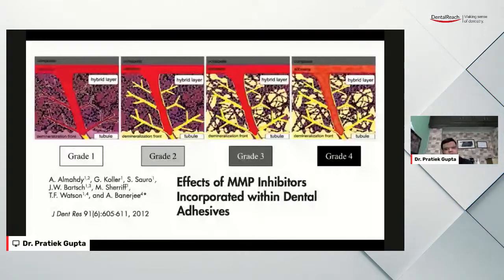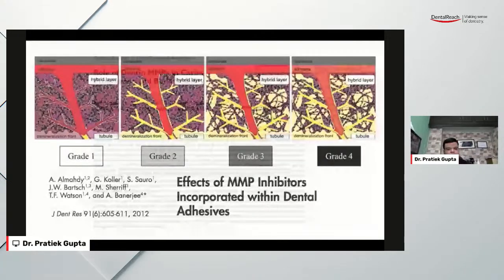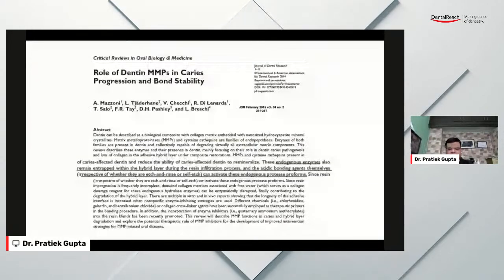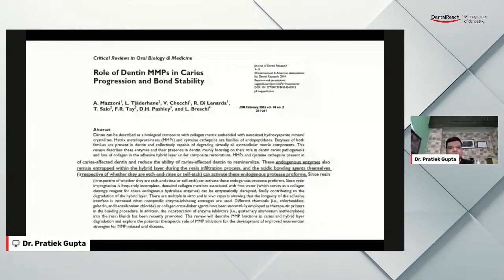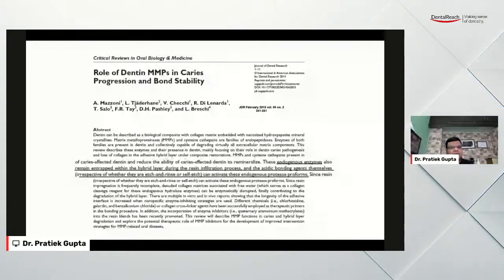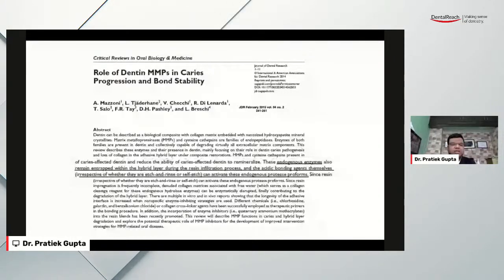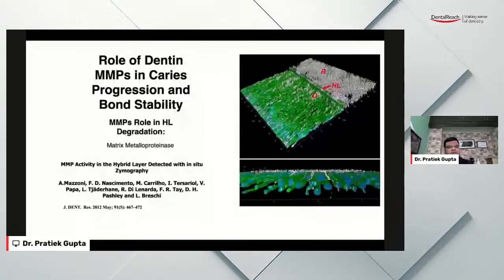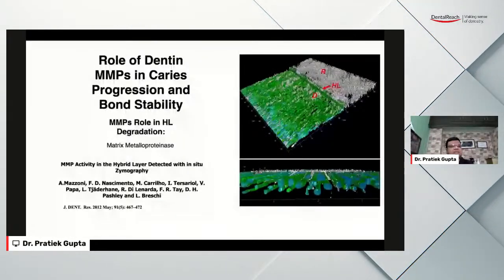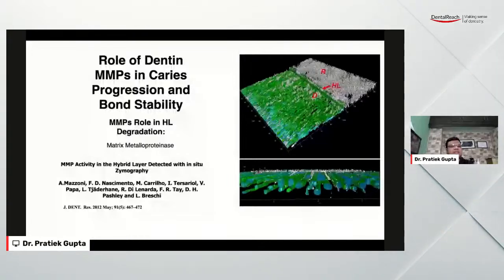Look at what happens from grade 1 to grade 2 to grade 3 to grade 4. Slowly, over a period of time, the adhesive layer just breaks. And what this leads to, look at this. Role of matrix metalloproteinases in caries progression and bond stability. Let me zoom that up for you. Endogenous enzymes remain entrapped within the hybrid layer during the resin infiltration process, when the resin is infiltrating inside. And these also deteriorate over a period of time, leading to caries. Role of dentine MMPs in caries progression and bond stability.